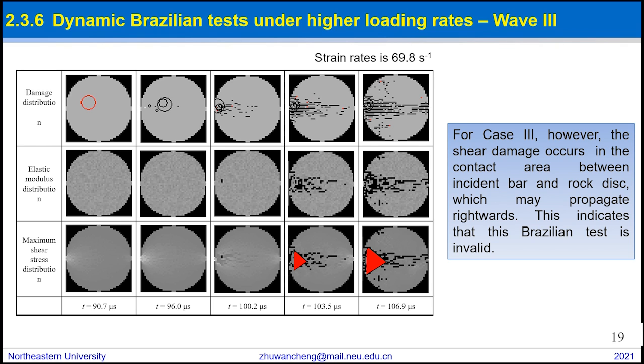In this regard, the first damage in tension does not initiate at the center of the sample, and the failure of rock disc is not dominated by the tensile damage along the horizontal diameter. Therefore, the failure process under the wave 3 becomes an invalid Brazilian test for obtaining the tensile strength of rock.